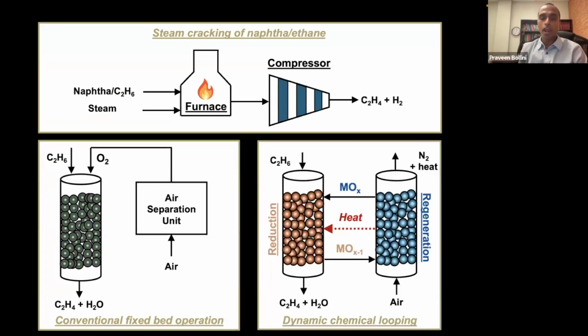Something that is a way of circumventing this need for an air separation unit is to use chemical looping as a reactor form in order to produce light olefins such as ethylene. So what you do in a chemical looping reactor, rather than operating at steady state in a conventional fixed bed, you expose your catalyst to ethane to produce ethylene and water in the reducer, and then you transport your catalyst particles into the regenerator, where instead of exposing it to oxygen, you're able to expose it to air to regenerate and reoxidize your oxygen carrier, then carry it back to your reducer, where you again generate light olefins like ethylene.